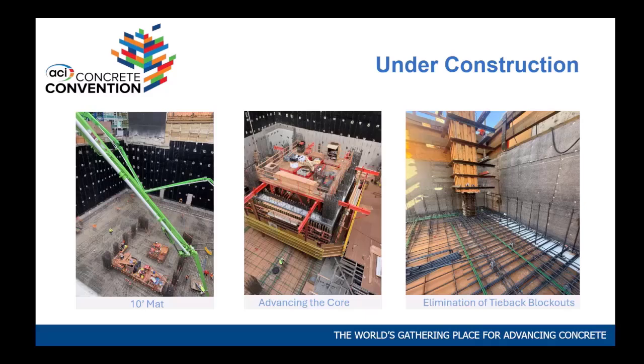for several months. One job we did, they were in the hole, they came to go down and up, took them a year. So what we do is this is actually the shoring system, that's not concrete. We allow them to put the slabs against the shoring system, and then what they do is they detension, there's tiebacks on the shoring system, they detension it, now the slab becomes bracing the shoring system, not the tiebacks, so you don't have to do blockouts in the basement wall. And then you don't do the basement wall till later, so these are formwork put at the joint of the basement walls. You have a basement wall above, basement wall below, slab in, and what they do is they come back later when the tower is up to level 2, they come back and shoot with shotcrete the basement walls. And they're pretty thick basement walls, 16 inches.